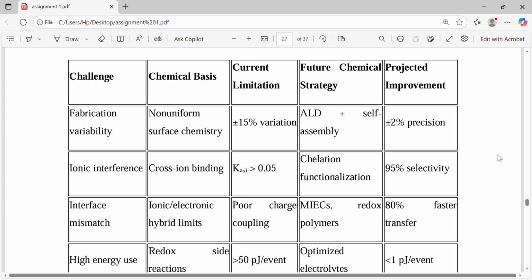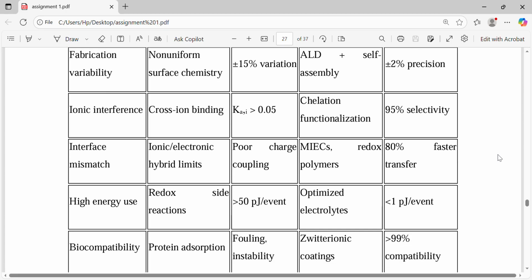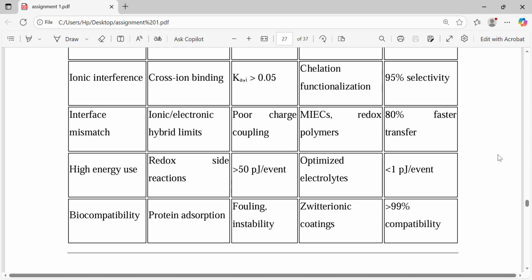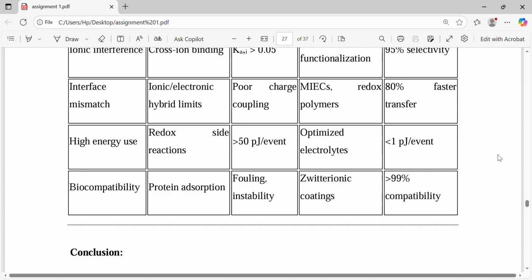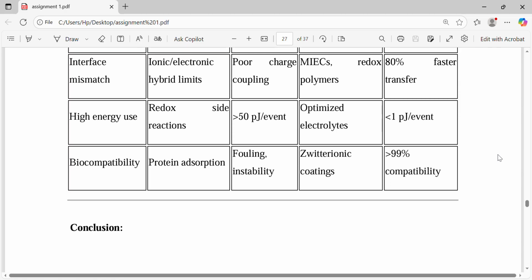Ionic interferences: cross-ion binding. Chelation functionalization, 95% selectivity. Redox side reactions, greater than 50 pJ per event, optimized electrolytes, less than 1 pJ per event. Biocompatibility: protein adsorption, fouling, instability. Zwitterionic coatings, greater than 99% compatibility.